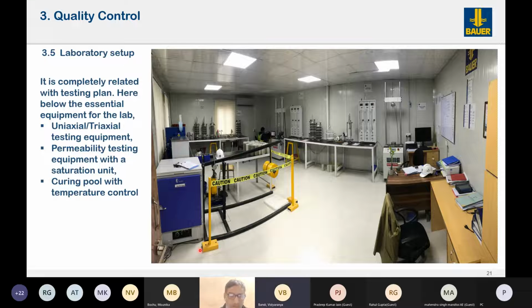We need to have a complete setup of the laboratory at the site to ensure that we are able to check the soil samples collected from the wet sampling and carry out uniaxial or triaxial compression testing on the samples so that we are able to establish the parameters of the soil, the modulus and the compressive strengths. We can also check for the permeability of the samples and the curing. So for all this, because we are using cement, we have to ensure that all these samples are cured for 7 days, 14 days, and 28 days categorically.